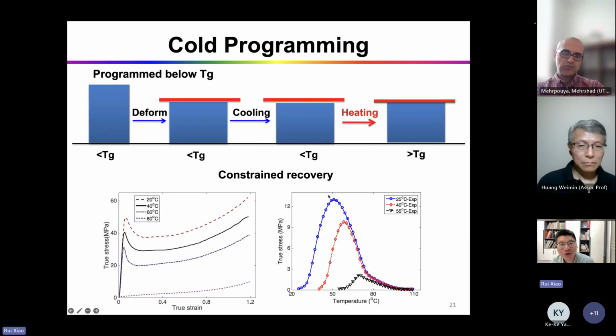So we typically know the recovery force for shape memory polymer is really low compared with shape memory alloy - it's very low. But if you program below TG, it actually can produce very large stress.